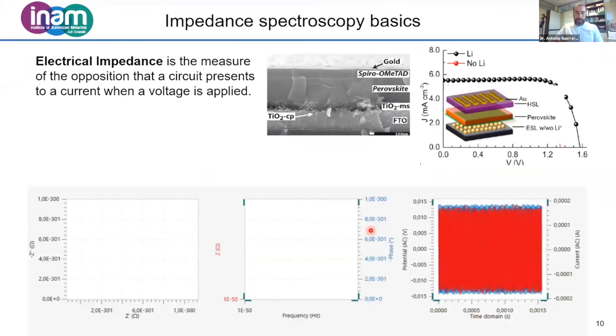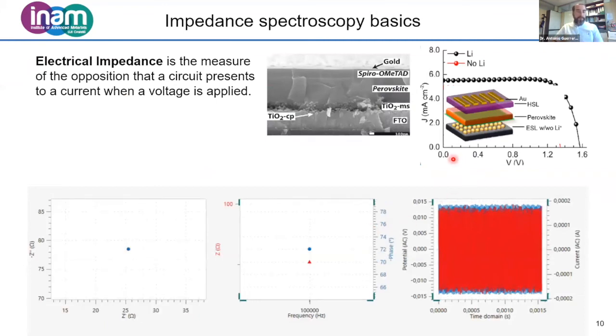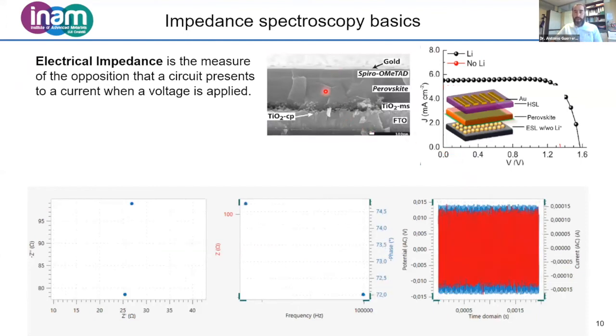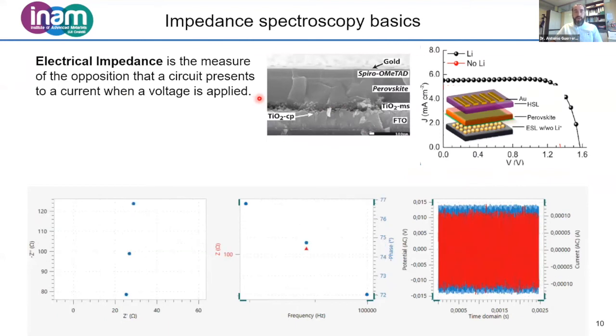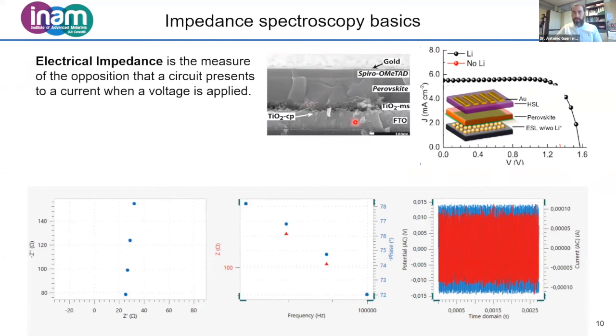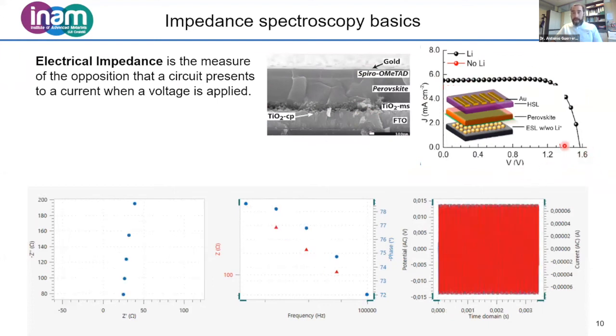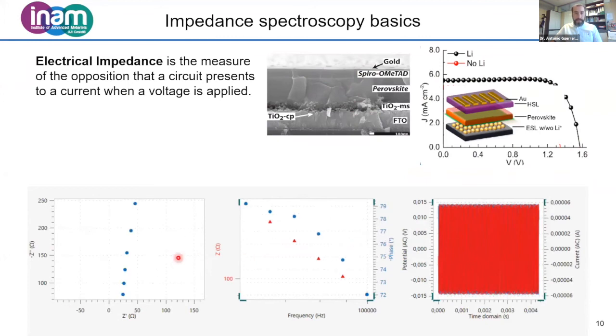Now I show you some actual impedance spectroscopy measurements, done on lead halide bromide perovskite with this configuration: titanium dioxide, perovskite, spiro, and gold. This is the JV curve we get. We get very high VOC. And here you see three plots.